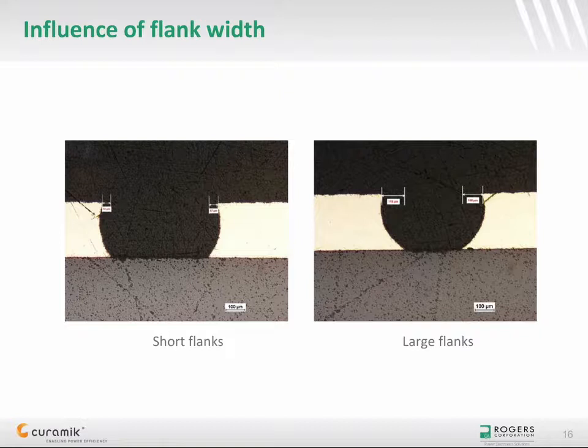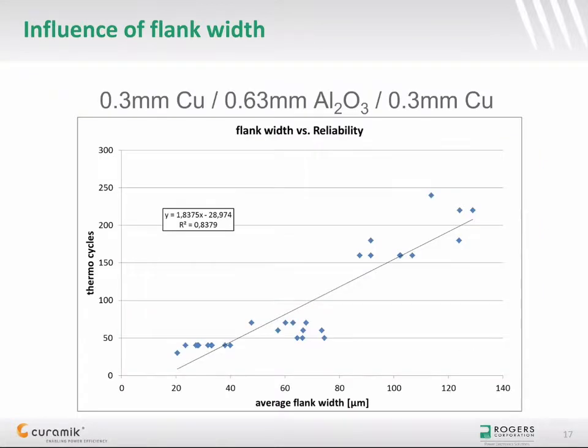As you increase the etching time, the side walls of copper pattern will become shorter and shorter, and this leads to even more stress concentration at the edges of copper pads. A study was conducted at Rogers for a standard material combination. Results indicate that there is almost a linear correlation between the average flank width and the number of temperature cycles. According to our design rules, the flank cannot be larger than half the copper thickness. For 0.3 mm copper thickness, it can be max 0.15 mm, and it should be as close as possible to this value to guarantee the best possible reliability.